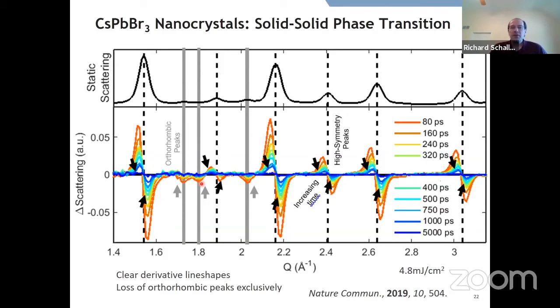So this is something suggesting that we're not just seeing disordering. The material is still very crystalline, which is why you have these nice derivative type features over here. These guys are not very asymmetric. So we're not just disordering everything. What you're doing is driving the system optically from one crystal phase to another. And this is relevant because the material shows gain and lasing. And what it can be suggestive of is that you're actually getting lasing from a phase that is not the one that you're pumping. Your material itself is undergoing phase transitions that there may be lasing from.